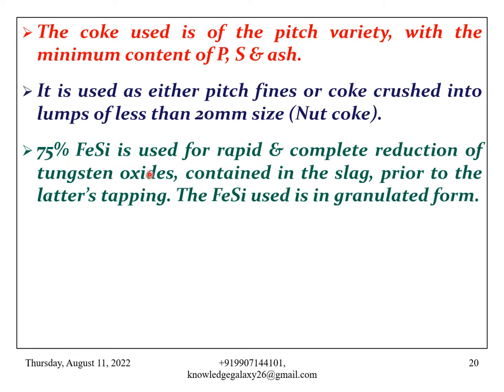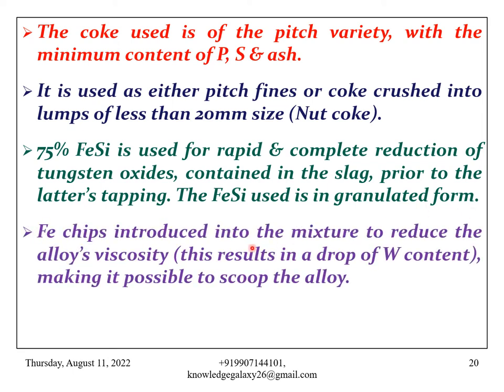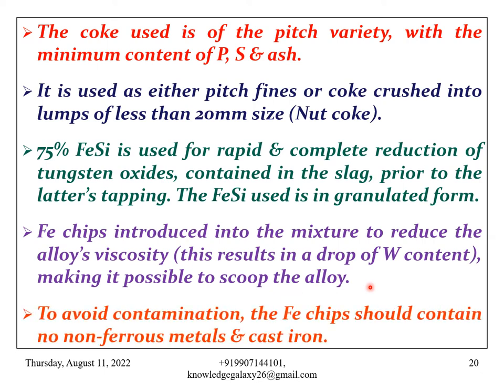75% ferrosilicon is used for rapid and complete reduction of tungsten oxides contained in the slag prior to the latter's tapping. The ferrosilicon used is in granulated form. Iron chips are introduced into the mixture to reduce the alloy's viscosity. This results in a drop of tungsten content, making it possible to scoop the alloy. To avoid contamination, the iron chips should contain no non-ferrous metals and cast iron.